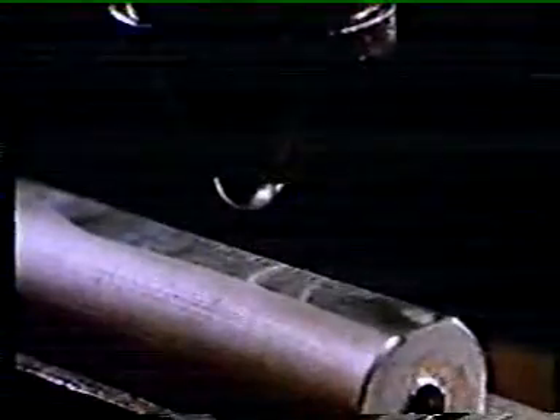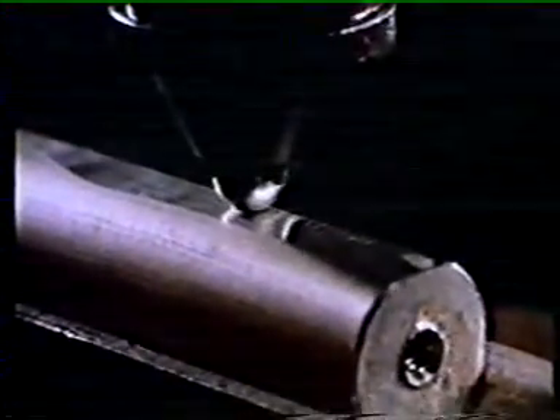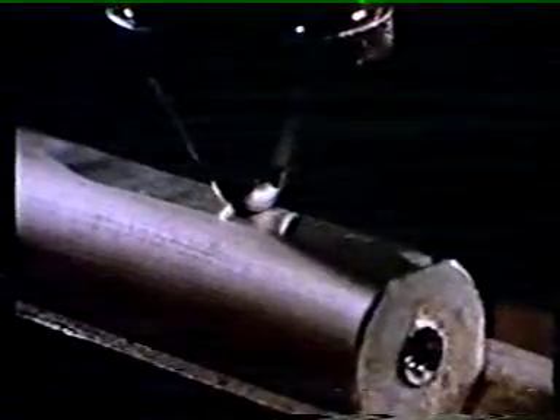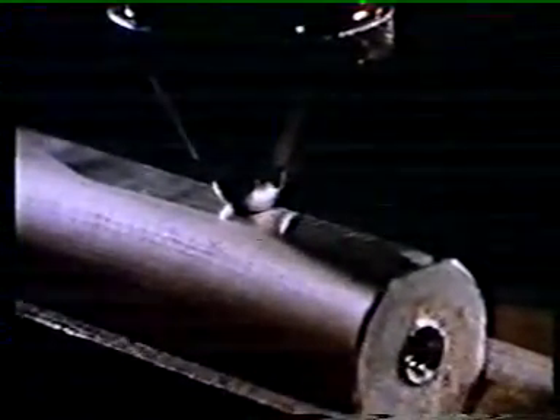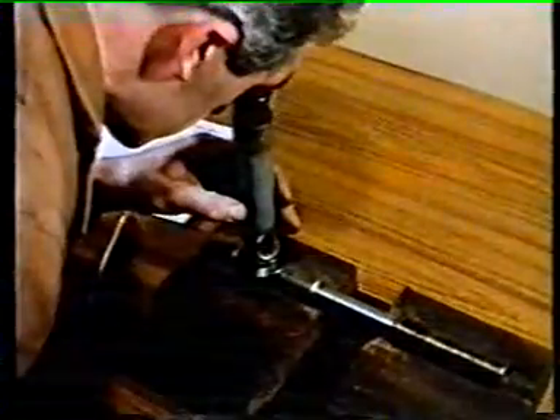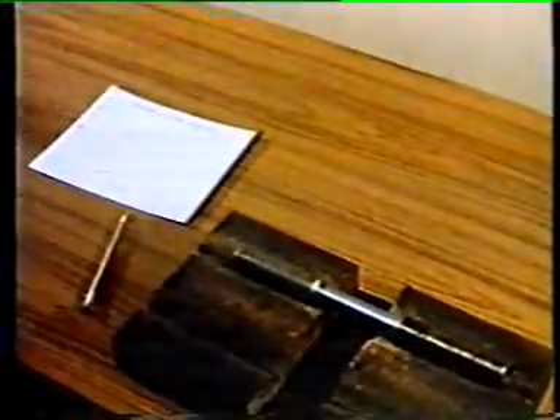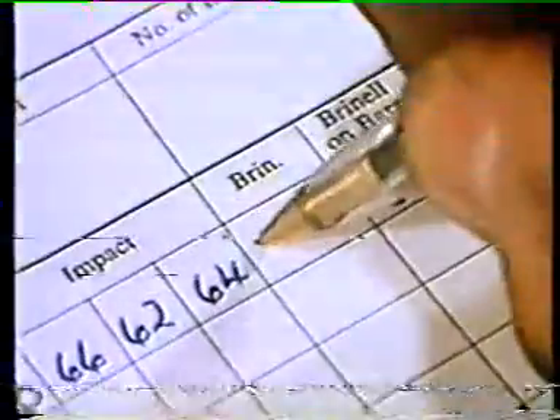But how hard is it? How ductile? A sample is cut from the batch and sent to the testing laboratory. A section is cut from the sample, and standard test pieces are prepared. Hardness can be measured on this instrument, in which a 10mm steel ball of extreme hardness is impressed into the surface of the test piece with a standard load of 3,000 kilograms. The diameter of the impression made by the ball is measured. The smaller the impression, the greater the hardness of the steel.